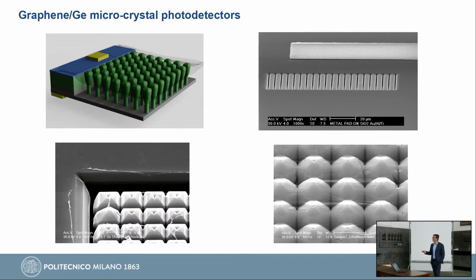And these are two examples. The first one is very bad: no graphene, just some small broken parts. Essentially, the problem is that since the spacing between these crystals is very small, we have extremely strong capillary forces. So the strongest material on Earth, as graphene people like to say, breaks due to these capillary forces. And so Virginia, the PhD student who did this, spent a lot of time in the clean room to find a way to obtain a continuous layer. And there you can really see graphene like a curtain on this microcrystal.